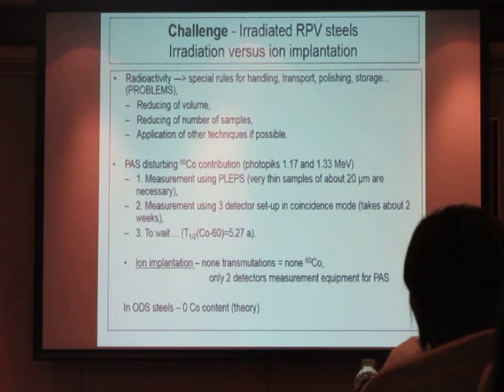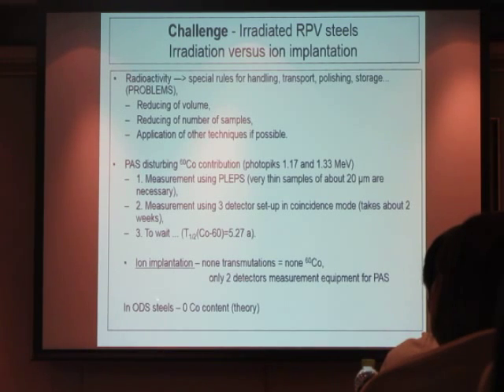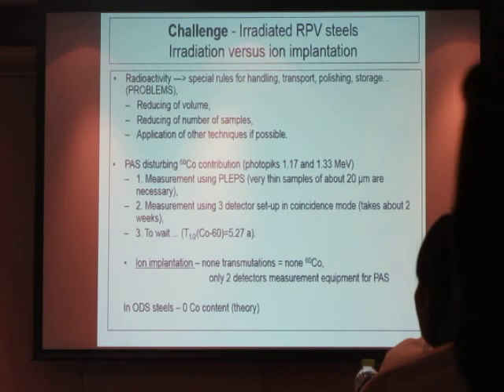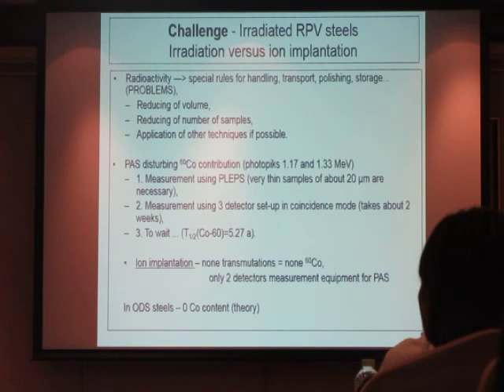Of course, the previous speech was about ODS steel. There is declared 0 cobalt content. It's not true. A small amount is in each steel. So this approach will perhaps be used in the future also for ODS steel. I know that the level of cobalt in ODS is perhaps 3 orders lower, but it's still there and still disturbs the results.